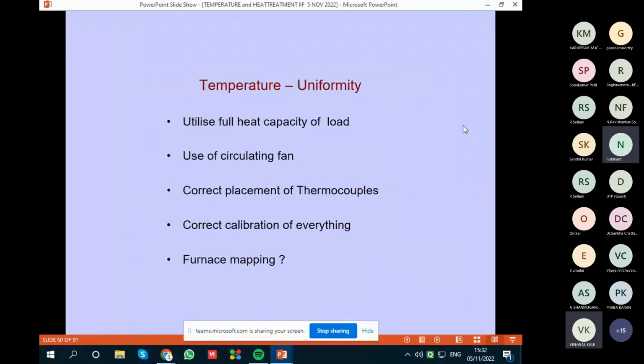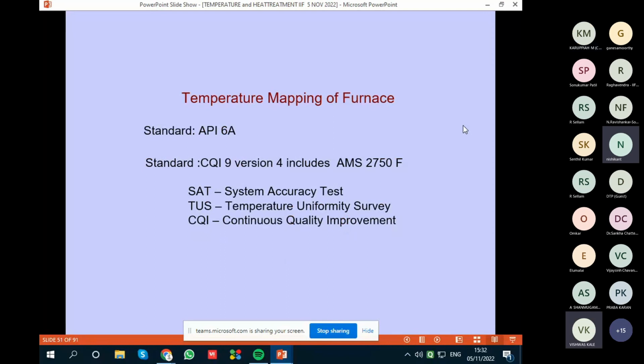So for getting uniformity, the simple rules are: utilize the full heat capacity of the load, use a circulating fan, correct placement of thermocouples, correct calibration of everything, and do furnace mapping. So let us talk about furnace mapping. There are two versions today, API 6A and CQI 9 version 4, which now includes AMS 2750F, which has come very recently. I generally recommend foundrymen to go in for API 6A first, because if you have not done mapping at all till today, it is better to spend less money, get some idea of the furnace behavior using API 6A, then make some necessary corrections in the furnace, and then check as per CQI 9.